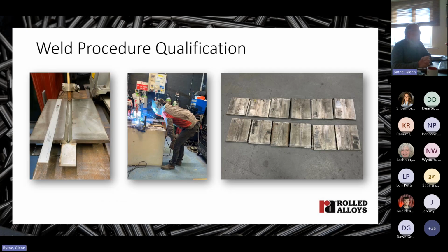Now, just a few words on weld procedure qualification. It's important to qualify weld procedures and welders as being capable of achieving the microstructural quality in the joints. Welding procedures are usually qualified to ASME 9, but like the ASTM standards, this omits corrosion tests, microstructure tests, and impact tests. So these tests need to be included as supplementary requirements to the fabrication specification to ensure that the welding parameters and welding techniques used are good.